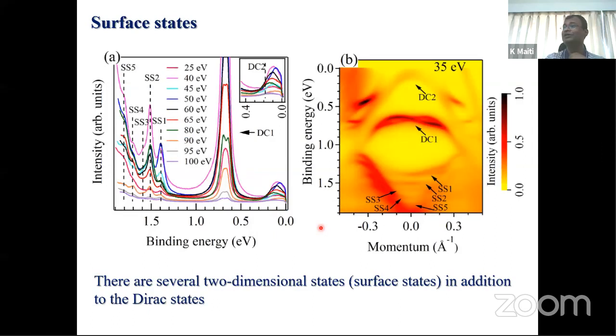We then looked at these EDCs at this S point, and we see that at different photon energies, the peaks are not shifting. So we found that this is a Dirac cone, this is another Dirac cone, and there are many additional surface peaks, which correspond to the surface electronic states. The other things, you see, are bulk.